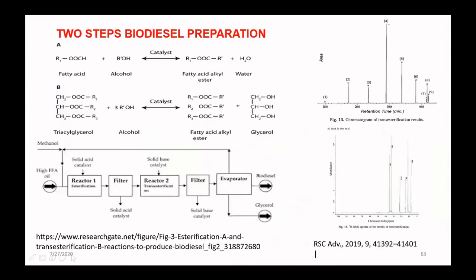Next is the two-step biodiesel preparation. In case the concentration of free fatty acid (FFA) is high, more than 5%, some researchers stated more than 3% FFA in vegetable oil is dangerous for making biodiesel. So we must decrease the concentration of the free fatty acid using pretreatment. Usually we use an acid catalyst to decrease the fatty acids in the first step, and we obtain fatty acid alkyl ester and water.